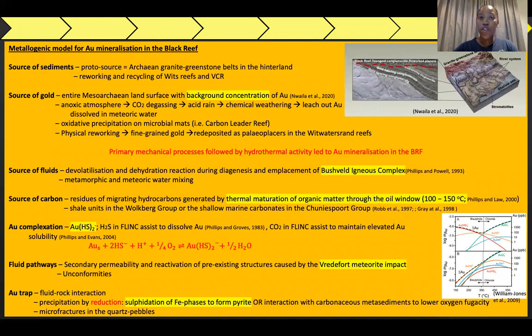The carbonaceous material in the Black Reef Formation is described as residues of migrating hydrocarbons generated by thermal maturation of organic matter through the oil window, which are temperatures reached, as shown by the fluid inclusion analyses of 172 degrees Celsius. The source of the carbon could thus be the shale units in the Wolkberg Group or the shallow marine carbonates in the Chuniespoort Group of the Transvaal Basin. And therefore, these are internally derived hydrocarbon fluids.